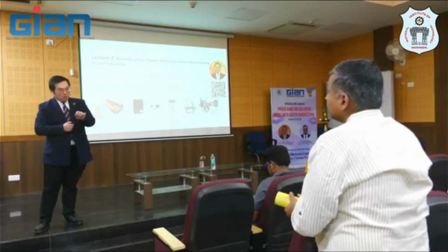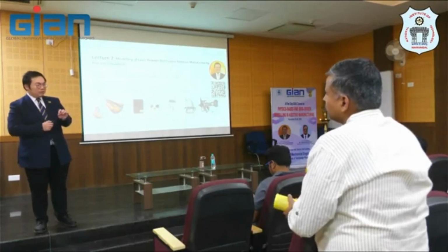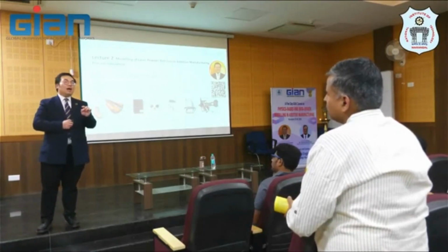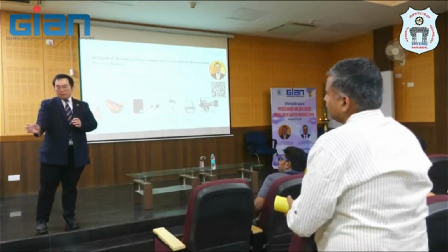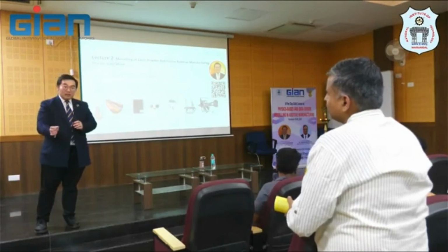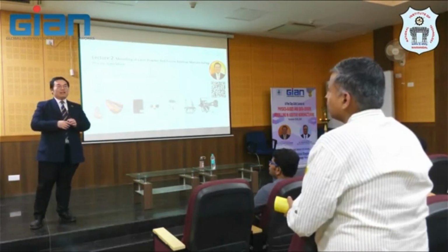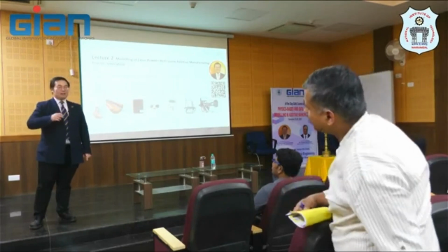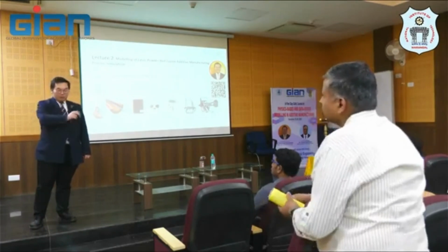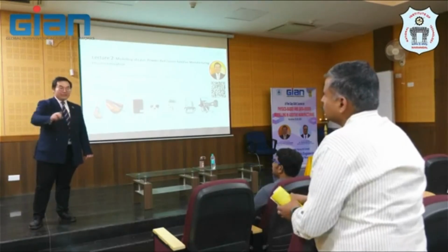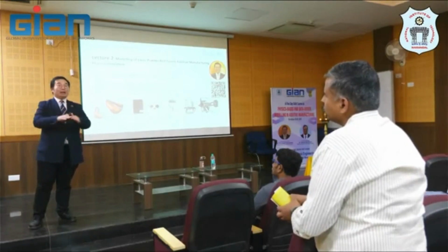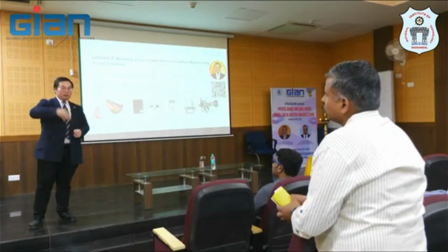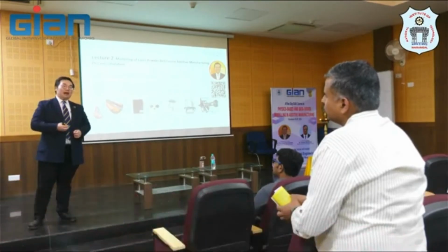If you follow some papers from Professor Körner from Erlangen University in Germany, she is using electron beam melting to fabricate about 5 millimeter thick single crystals. It already happened. The thing is they use a scanning pattern to mimic a spiral, so they scan like this. And then the thermal gradient is quite planar, and you can grow single crystal. But electron beam melting is a different process.